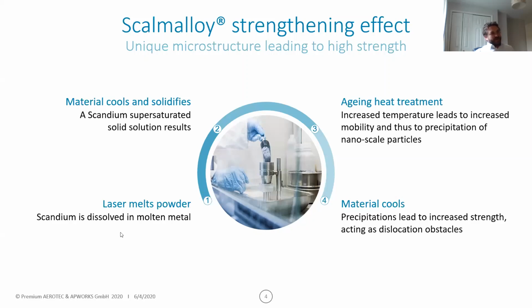So this is where it works very well with additive manufacturing, with laser additive manufacturing, because you have a very small melt pool with cooling rates of the order of, you know, you're talking millions of degrees Kelvin per second, rather than hundreds of degrees per second or something like that in a bigger melt pool. And this enables you to maintain this supersaturated solid solution of Al3Sc. I'm not a chemist. You're then performing an aging heat treatment, which is leading to this precipitation of these nanoscale particles.